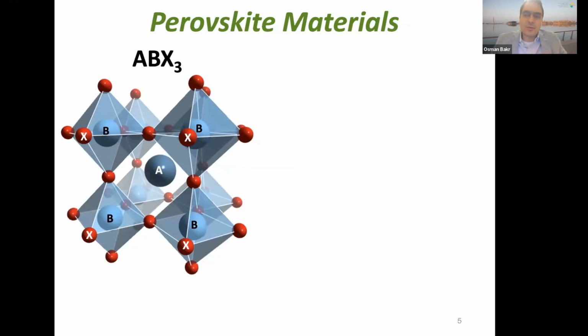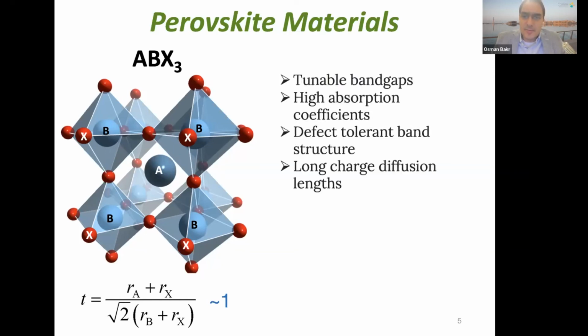First, let me tell you a bit about the material itself. Perovskites have this ABX3 formula. They're ionic compounds, where B is in an octahedra of X and A is in the void that's surrounded by the octahedra. And almost 50% of the elements in the periodic table can form a perovskite. They just have to obey the tolerance factor that basically governs the relationship between the radii of A, B, and X. And if that tolerance factor is close to 1, then there's a good chance to form a perovskite structure.